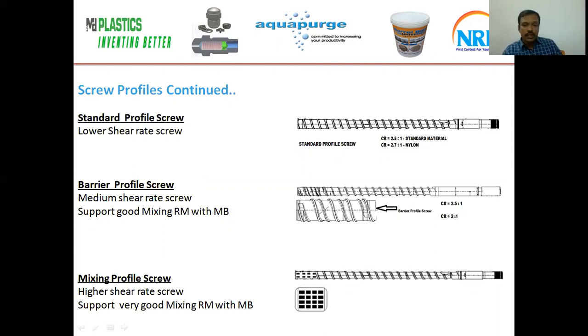See, if you process raw material with master batch with the standard screw, it normally causes improper mixing because it's a standard profile screw. So discoloration issues may come from processing that raw material with the master batch with the standard screw. It is preferred and suggested to process with the barrier or mixing profile screw to prevent molding issues such as discoloration. See, if you process any engineering material with a mixing profile screw, because of the higher shear rate, the molding defect of burn marks may come on the molded parts. So the screw profile also plays a vital role in the injection molding machine for molding free from molding defects.